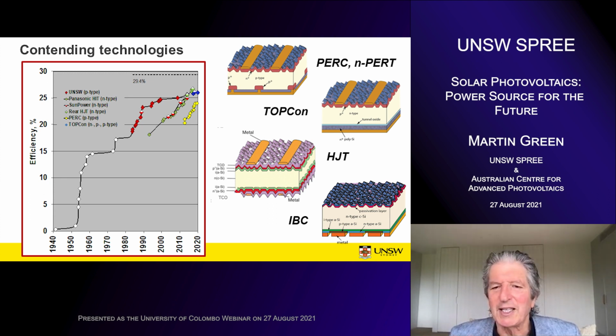Some of them are quite interesting, in that the one at the bottom there is the interdigitated back contact, but it has both contacts on the rear side of the cell, so completely different structure. I won't have time to go over these, excepting to mention there's a big competition between these now to see if PERC can hold its position as the dominant market leader, or will some of these other technologies knock it off its perch in the fullness of time. So the battle's on to keep improving the efficiency in production. The best manufacturers now with the PERC are doing over 23% efficiency. But eventually, I think the industry will do something like 27% efficiency with these technologies, very close to the 29% limit.